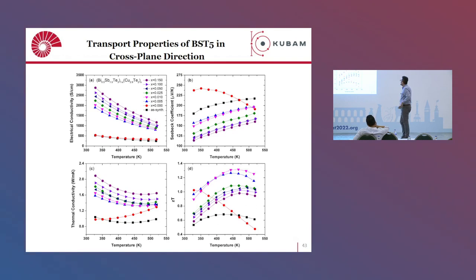So here are the transport characteristics. This is the undoped material, with low electrical conductivity. If you dope it with copper telluride, you can really tune it with the copper telluride amount, and the electronic conductivity goes up all the way. The Seebeck coefficient is high here because the carrier concentration is probably low. As you increase the copper telluride amount, the carrier concentration probably gets higher, for example through copper doping, and the Seebeck coefficient gets lower. Thermal conductivity, of course, since it is a metallic material, increases as well with metallicity.